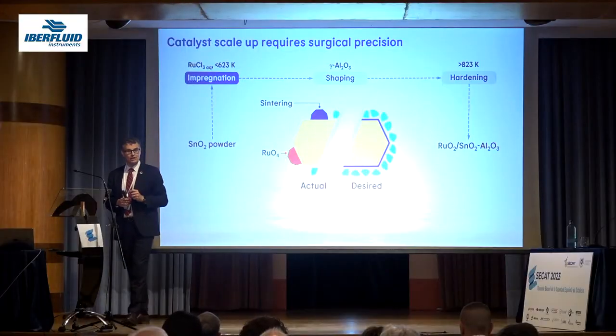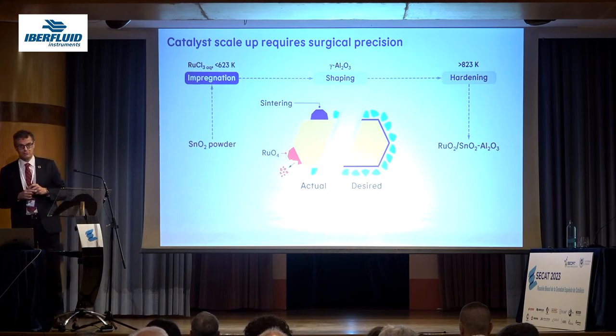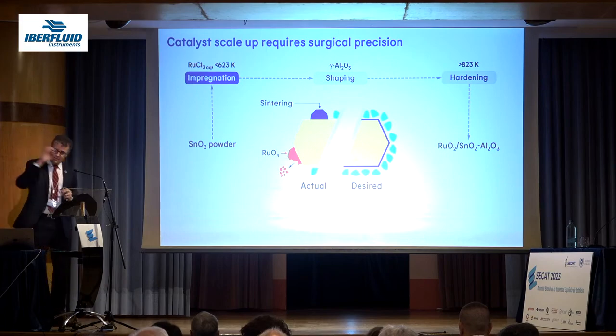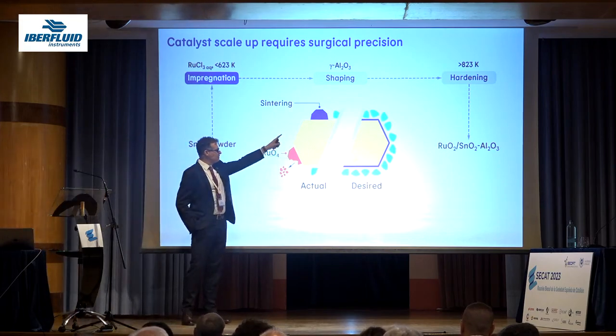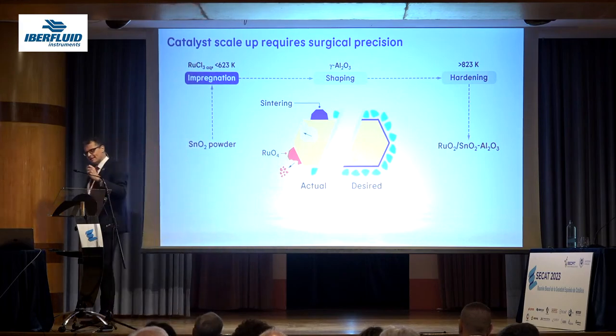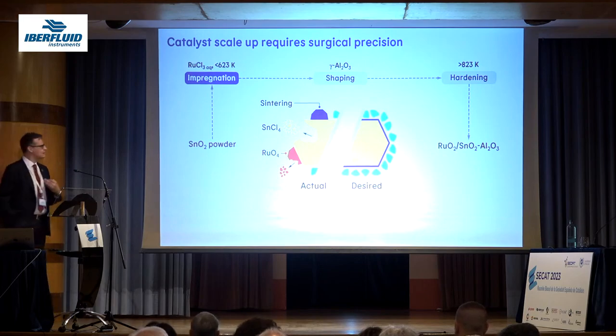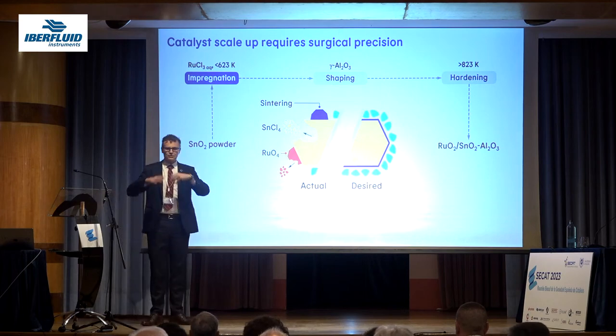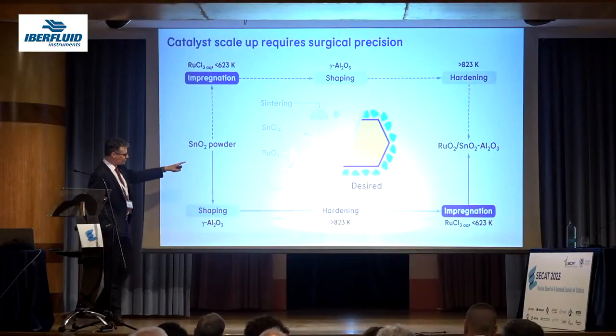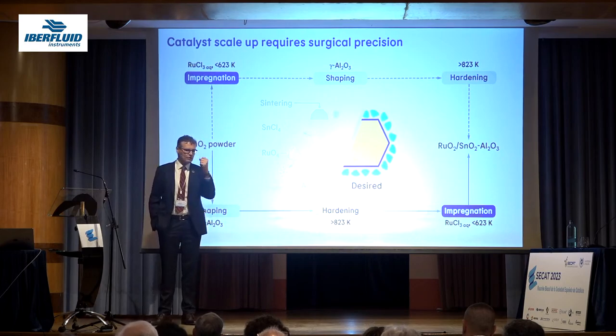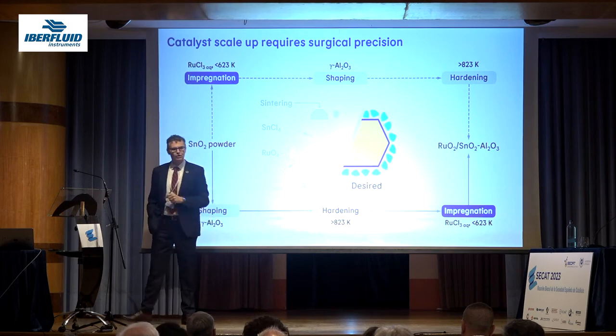What happens when you sinter ruthenium oxide is bad for 2 reasons. The high temperature actually transforms ruthenium oxide into ruthenium tetraoxide. Ruthenium tetraoxide is even more volatile than ruthenium chloride. So you are losing your ruthenium. But there is even another terrible consequence, which is that when you break the layer, you leave tin oxide accessible to the HCl, and this is going to chlorinate. You produce tin tetrachloride, and tin tetrachloride is also very volatile. So all your beautiful understanding of 2 layers and coverages goes to the sink because you don't know how to make a recipe that can produce tons of these materials through fundamental understanding, not just trial and error. And so the way to do it is actually to shape first and to harden, so you expose the catalyst to the high temperature before you put the ruthenium, and you only put the ruthenium at the very end.